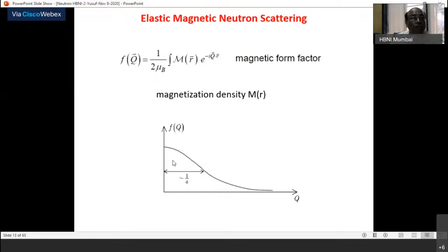when you do neutron diffraction for magnetic material, when you look for magnetic Bragg peaks, you have to always design your instrument in such a way that it is able to measure from relatively lower 2 theta, and the instrumental resolution is better over this lower 2 theta range, because your intensity is anyway going to fall after a certain q, after a certain 4 pi sin theta per lambda, after a certain 2 theta scattering angle.